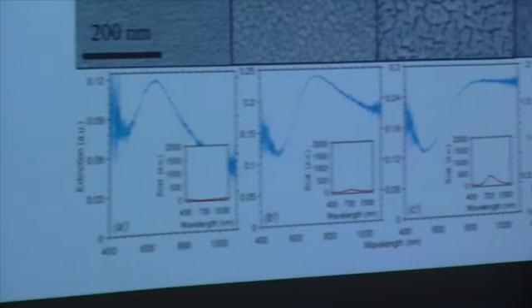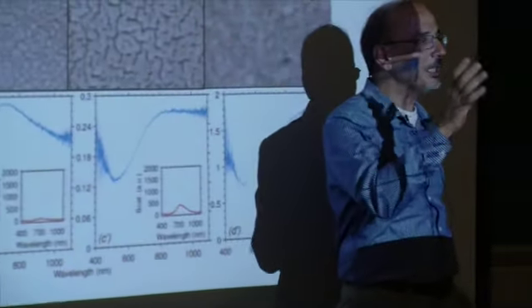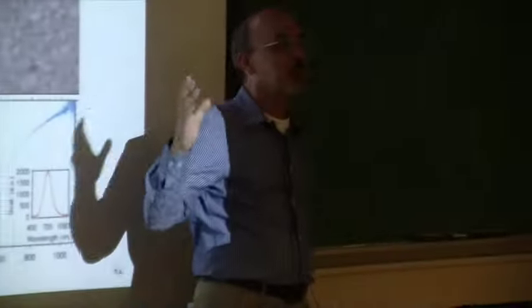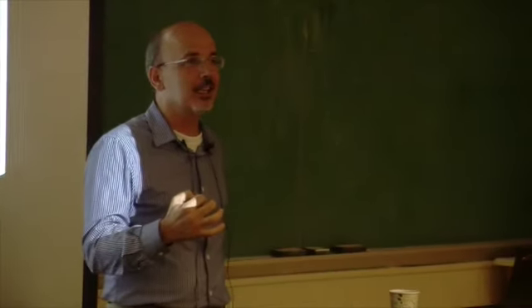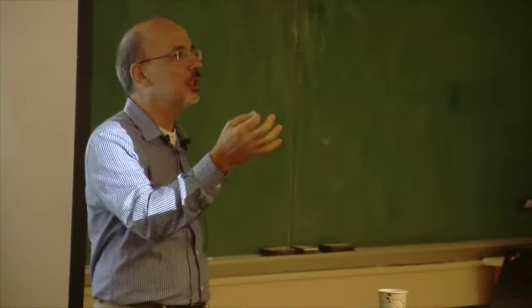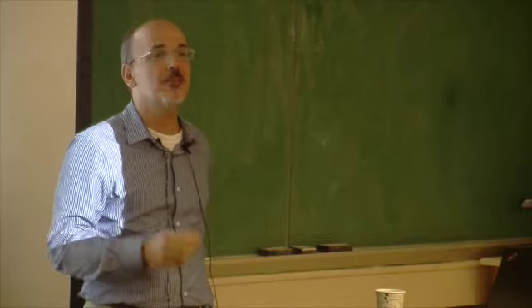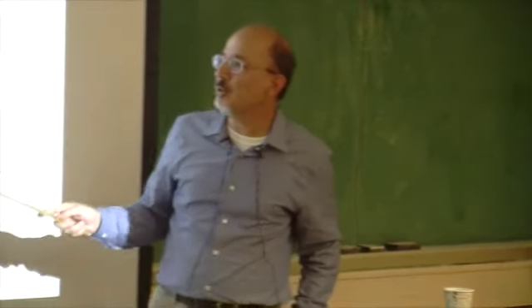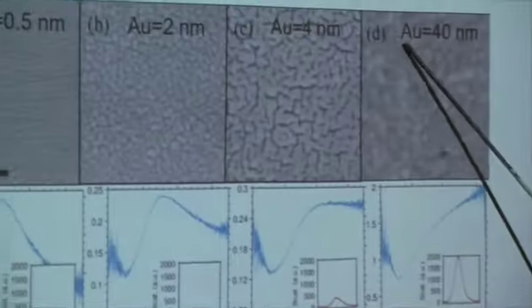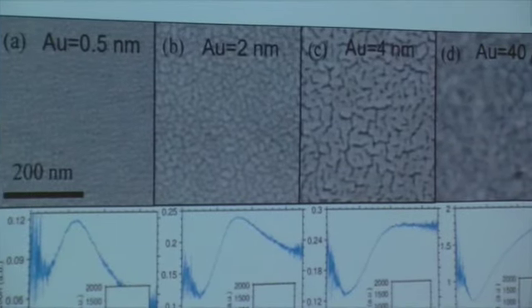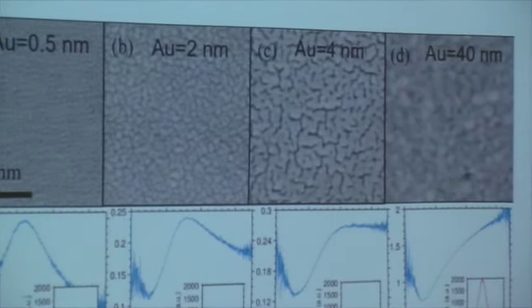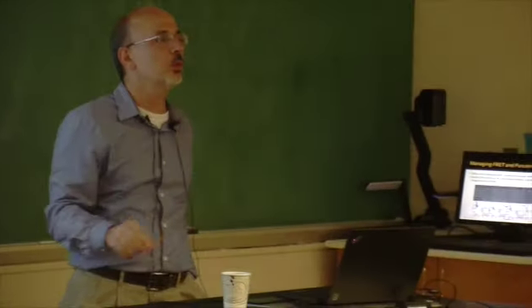This is the plasmonic peak, and it is right at the wavelength of the quantum dot. So when the quantum dots are excited, they deliver the energy to the metallic nanoparticle very fast. But then as you increase the thickness to 40 nanometers, we cannot even measure how much extinction we have, because 40 nanometers of gold absorbs so much light.